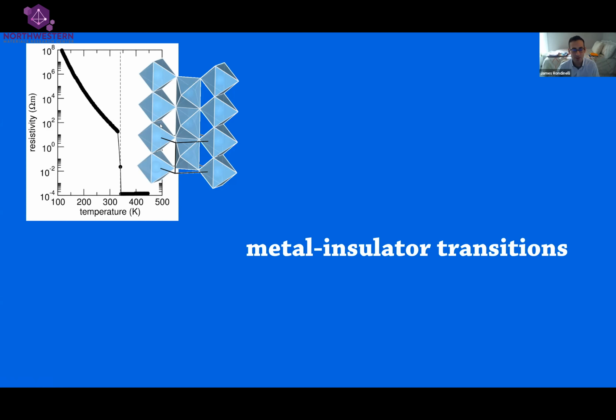So what I have in the upper left of this slide is a crystal structure. So this would be a compound which comprises octahedra. And in the projection I'm showing you, you can see that the octahedra share an edge. So they're connected together by an edge. And these edges are connected in one-dimensional chains. And so this material is quasi one-dimensional, even though it's a 3D crystal. Okay, and the specific material for which I'm showing the electrical resistivity as a function of temperature is vanadium dioxide, so VO2. And vanadium dioxide adopts this structure, and this structure type is known as rutile.